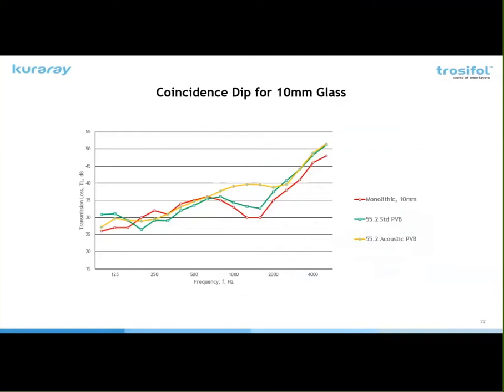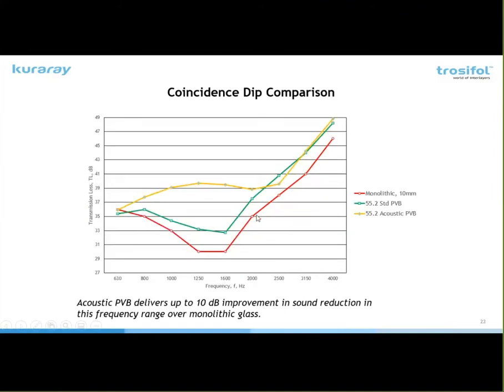Basically, in glass, there's a coincidence dip. And the coincidence dip is determined by if you take the thickness of the glass and divide that into 12,500, you'll see where the coincidence dip is. So this is actually for 10 millimeter glass. You can see the coincidence dip is right around 1250 hertz. And you can see most of the area, it's pretty close, except here.